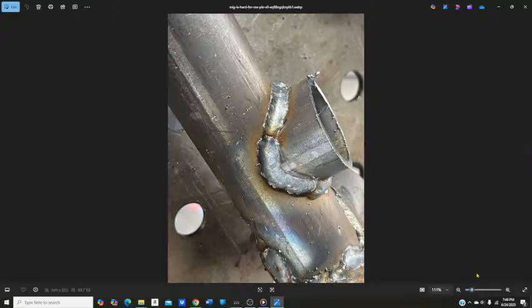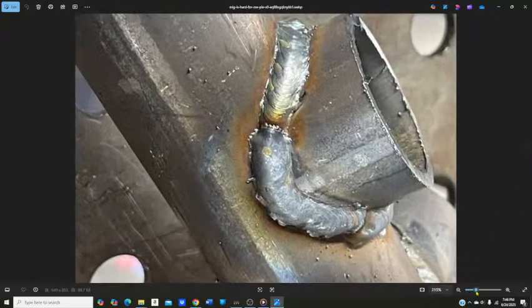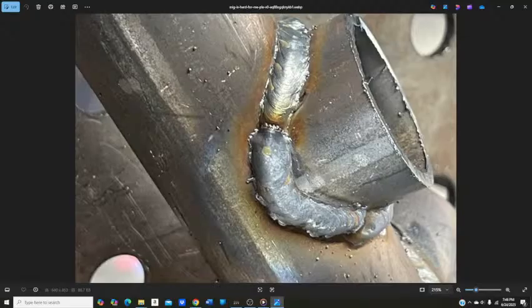Now here is a MIG welded joint. So this is not done well here. This is not enough heat, so the weld is puddled up on top of the metal, and it didn't melt into the two pieces of metal. So this section of pipe right here, there's nothing holding it. If that was the way the weld was all the way around, you could smack this with a hammer and it would fall right off. But this section right here is a decent weld.